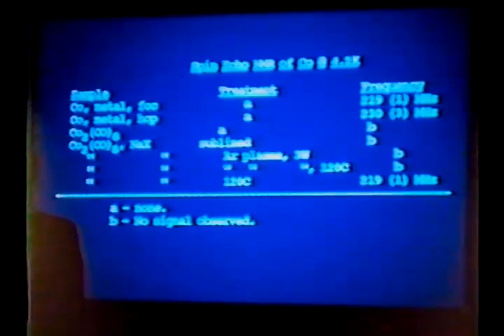If you take these particles and heat them to 120 degrees centigrade, you don't see a signal. If you take the cobalt carbonyl and sublime it into the zeolite, don't treat it in the plasma, but heat it to 120, you do see a signal. And what that tells us is that just thermally heating the material is a different route than the plasma route. But the plasma has somehow stabilized those small metal particles in the zeolite. We're glad to see this. We've been saying this from indirect catalytic experiments for years. But here's a pretty direct measurement to say that there's a big difference between thermal activation and plasma activation. Not just from catalytic data, from spectroscopic experiments as well.